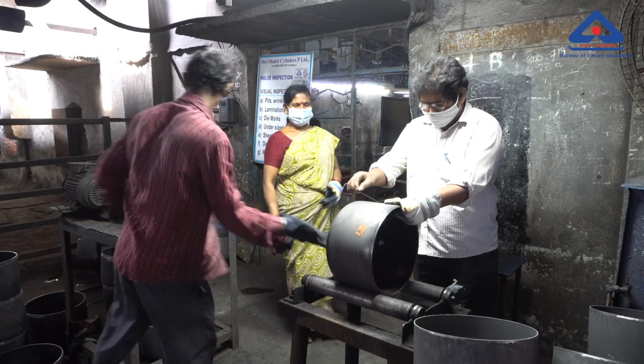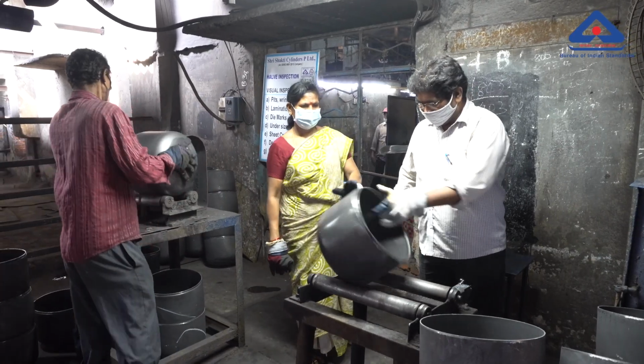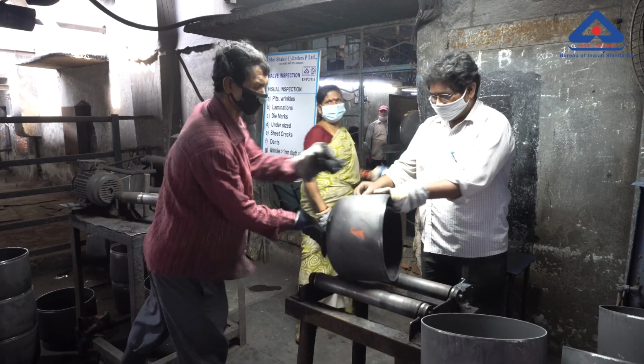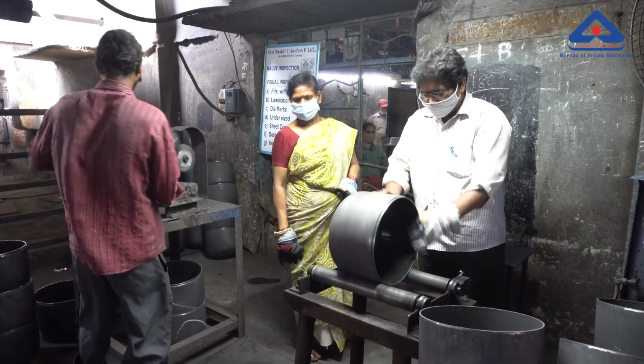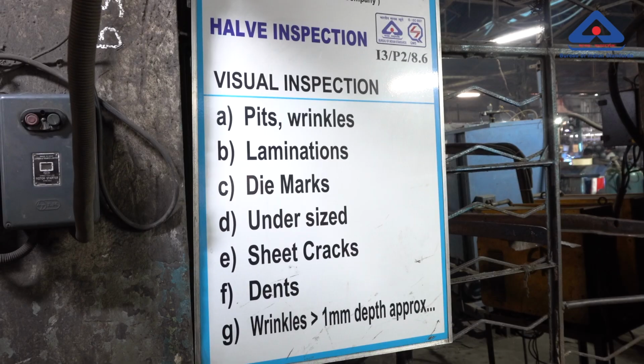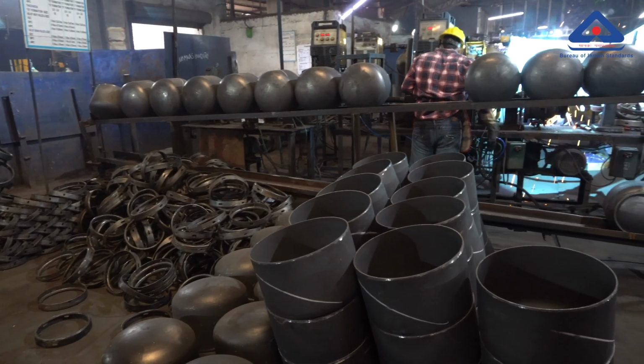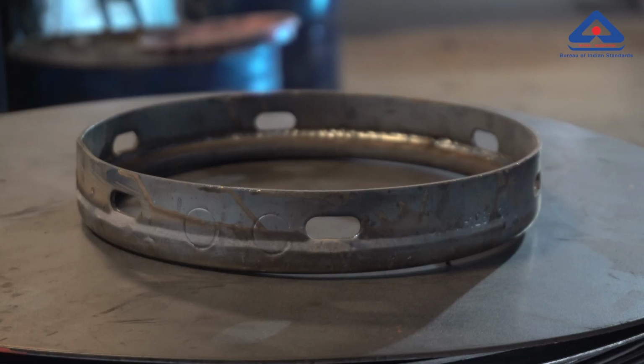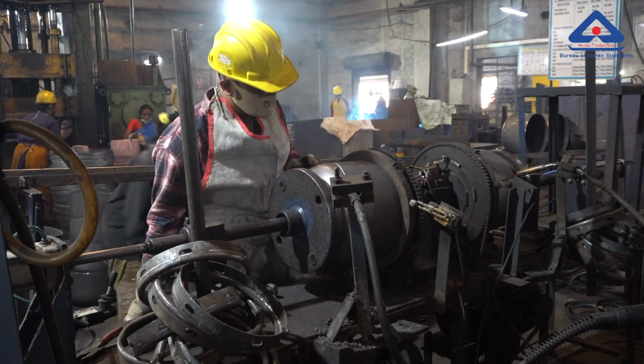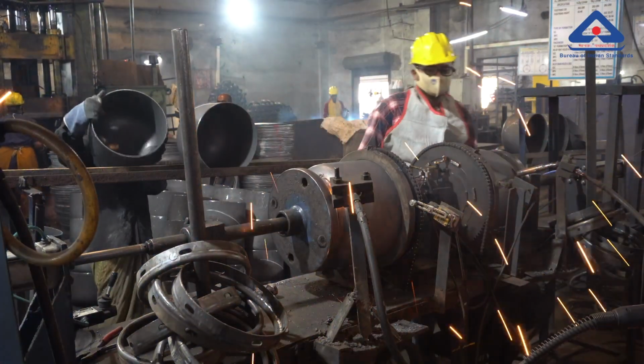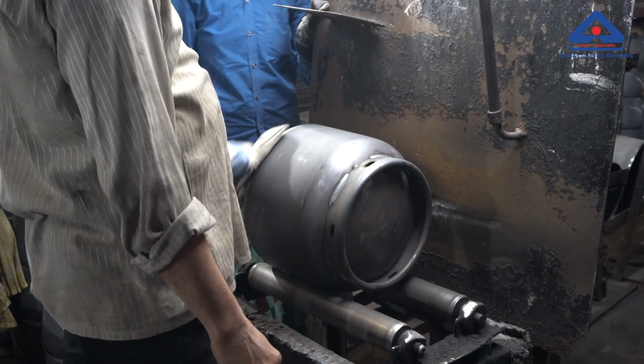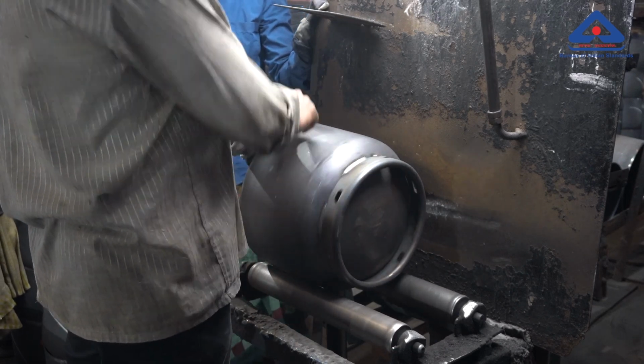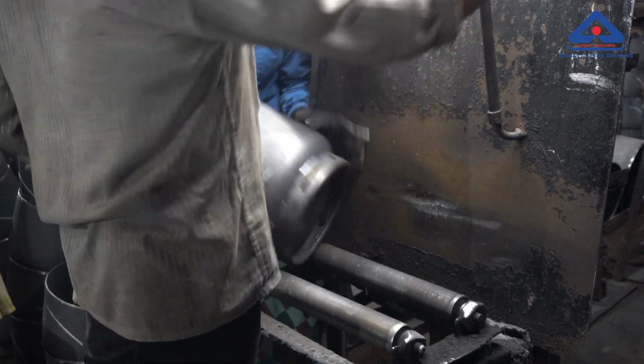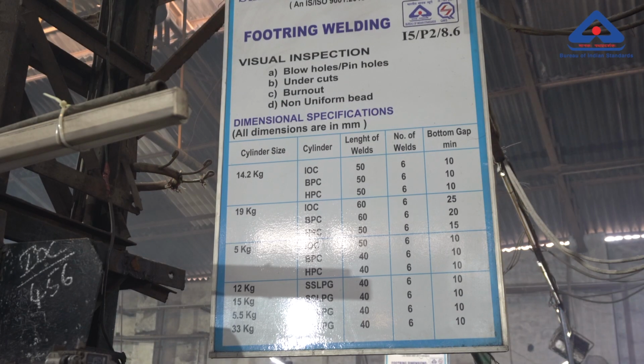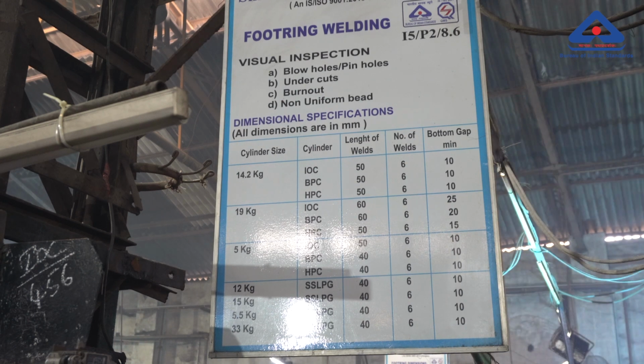Every half is carefully checked in case it has any crack, dent or die marks. If there is any defect, then that half is instantly discarded and the cause is identified with strict measures. The halves which are not having the holes at its bottom are taken for foot ring welding operation, in which foot rings are welded with the help of automatic welding machines. Every half is again closely checked for pinholes, undercuts, burnout and non-uniform bead. Once it is ensured that all dimensions are proper, it is taken to the next stage.